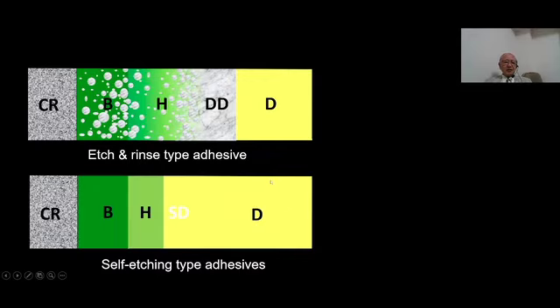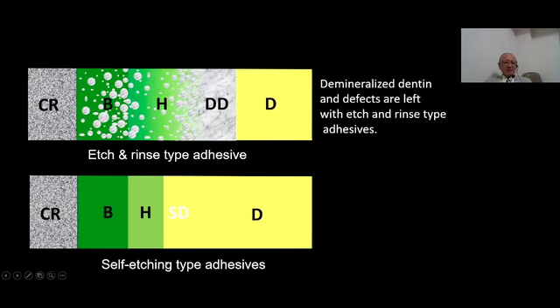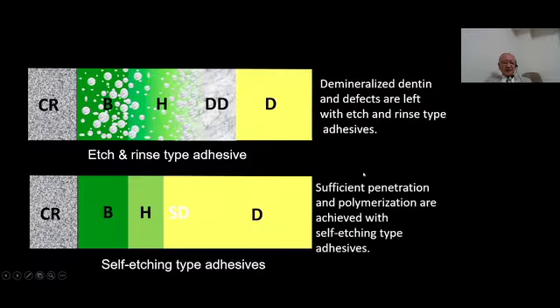Now I can show the difference of the bond interface between etch and rinse type adhesive and self-etching type adhesive. The demineralized dentin and the defects are left with etch and rinse type adhesive, even with primer application. But sufficient penetration of the bonding resin into the demineralized dentin was achieved with the self-etching type adhesive.